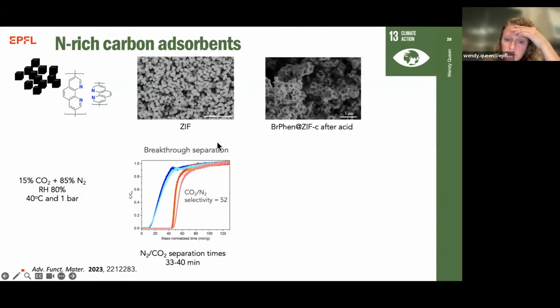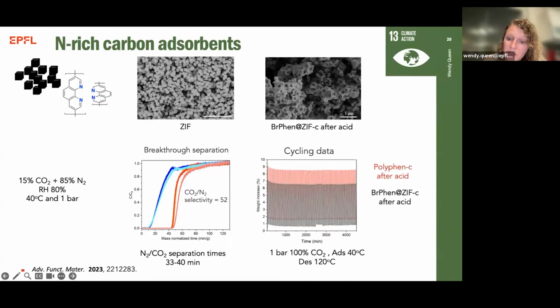And so from there, we've looked at the breakthrough measurements of the material. Here you can see the nitrogen breakthrough and then the CO2 breakthrough under both dry and humid conditions. The separation times range from 33 to 40 minutes per gram of material. Now, this is not nearly as high as our amine-based materials. However, we know that with these materials, our cyclability is likely to be much better, hence the reason that we're interested. Here you can see very strong cyclability with no decline, of course, in the material's capacity.